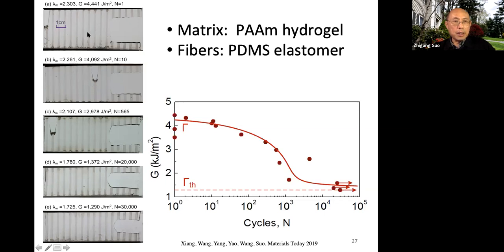So here is a photo. If you have a higher load, you have damage here. If you have a slightly lower load, you have some other form of damage. But if you are at this load, 1,000-some joule per meter squared, and after so many cycles, you don't see any growth, no growth. It's a threshold. So that's a very simple mechanism. All you need is a tough, hard and soft composite, and you have a high threshold. So I need to wrap up.